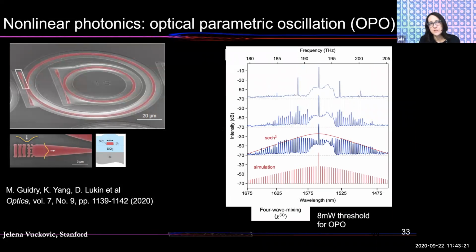Recently, we've also looked into optical parametric oscillation. We demonstrated that we can have OPO on silicon carbide with only 8 milliwatts of threshold. This is relying, in this case, on chi3 nonlinearity, but you can actually also build it with chi2 nonlinearity. And you can actually see even the signal of microcomb emerging in this case at higher powers.